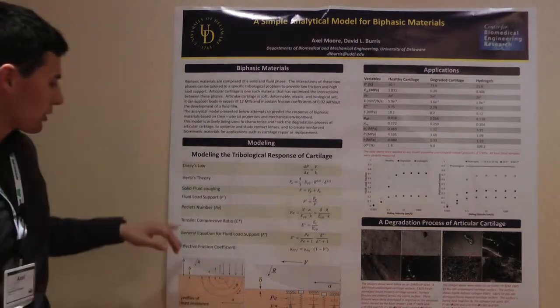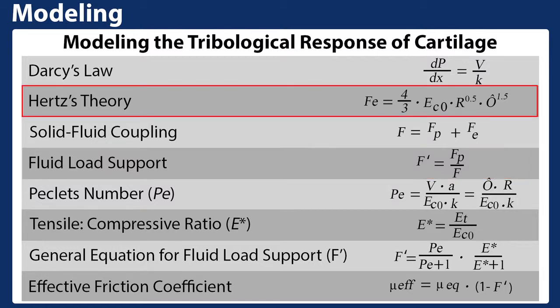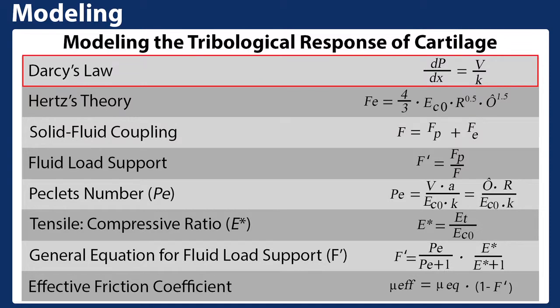That equation is shown here as a fluid load support fraction, which is just the fluid pressure support over the total contact load. The elastic load is solved by Hertz's theory, and we solved Darcy's law to get the fluid load support.